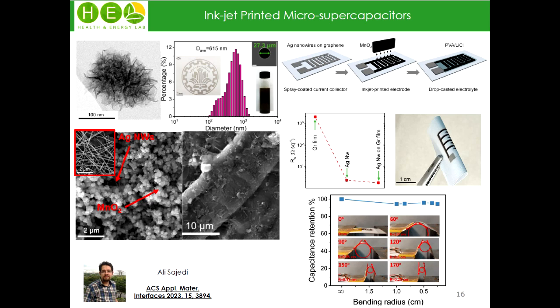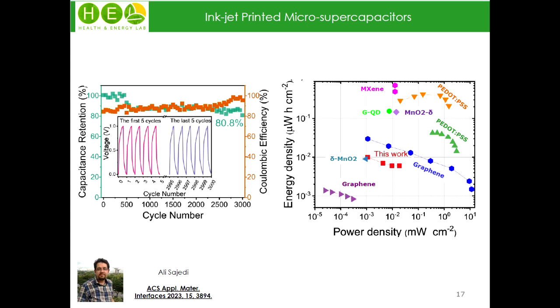The challenge we had for the solid state supercapacitor was applying gel electrolyte. There are issues in terms of diffusion at the interface of gel electrolyte with the electrode material, and this was the reason that hinders Coulombic efficiency or capacitance retention, but we are still working on this subject.